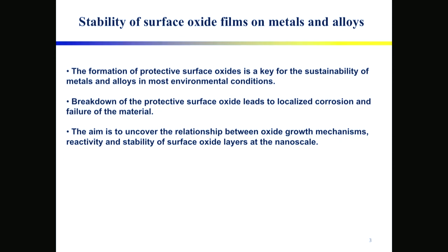So, stability of surface oxide films on metals and alloys. As I have stated already, the formation of protective surface oxide is a key for the durability or sustainability of metals and alloys in most environmental conditions, and this is also in most industrial sectors. The problem with these oxide films is that if they break down, and they do break down very locally, at a very local scale, or starting at the atomic layer or the nanometric layer, that can lead to localized corrosion and failure of the material and failure of the whole structure.